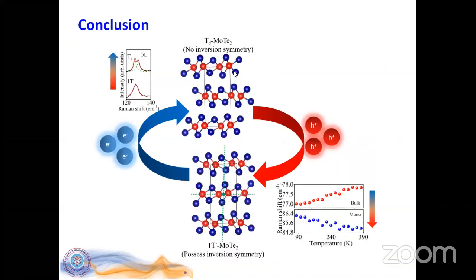And now this is where I'm going to draw the conclusion that we can find a way now to change the phase transition, or explore the phases, simply by hole doping or electron doping, even without really changing the temperature of the system. And that's what I try to say, that phase transition at will.